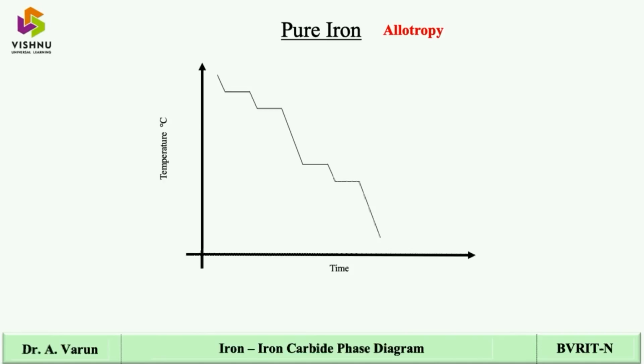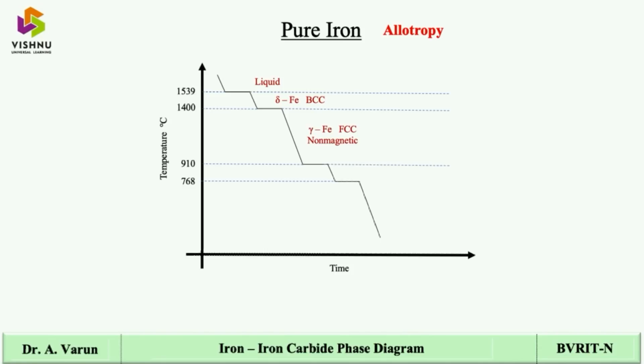And in this, very importantly, the temperatures need to be noted down. So it starts with 1539, 1400, 910, 768 degrees centigrade. Above 1539 degrees centigrade, the pure iron will be in the liquid phase. Below 1539 up to 1400 degrees centigrade, there is the first allotropic change of liquid iron to delta iron in BCC crystal structure for pure iron. This delta iron is in BCC, that is body centered cubic crystal structure, and below 1400 degrees centigrade up to 910 degrees centigrade it exhibits another phase change, normally called gamma iron, and it has a face centered cubic crystal structure which is non-magnetic.